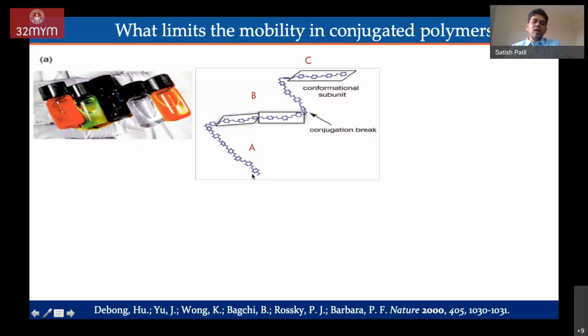These polymers can adopt a variety of conformations, and that essentially gives rise to defects. And these defects are extremely difficult to identify with characterization. And it's also difficult to repair these defects. When you design a material in the laboratory by chemical synthesis, these are all inherent defects. So when delocalization happens through these pi conjugated backbones, these defects essentially limit the charge carrier mobility. And they do adopt a range of conformations.